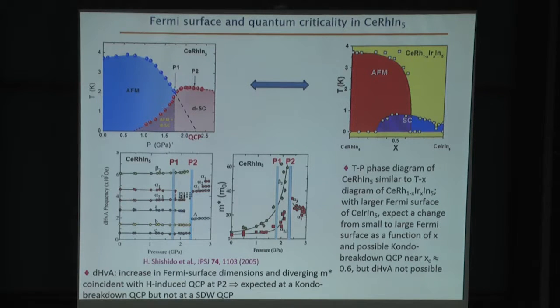What is not expected at a conventional spin density wave quantum critical point is this rather abrupt change in de Haas-van Alphen frequencies as we go from below this pressure P2 to above this pressure P2. And these changes are most pronounced in these dominant sheets of the Fermi surface that are labeled alpha sheets, where we see that the frequencies of these alpha sheets go from something around 4 to something much higher than 4, near 5.